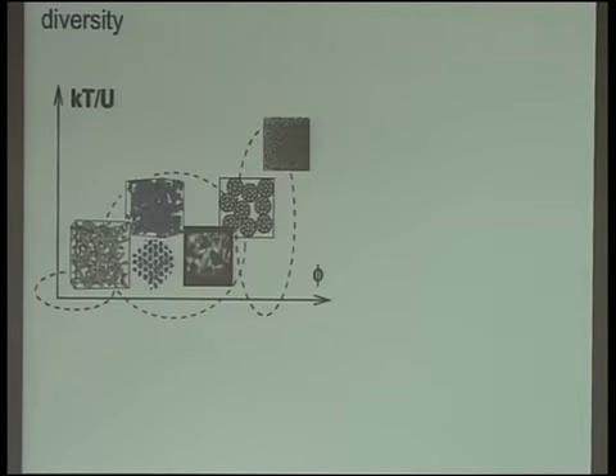Okay, so as I said, let's start from a case that is very typical of soft matter. You have a suspension of colloidal particles, and typically in experiments you can control very well the strength of the attraction between the particles, so you have particles that can stick together, and the solid volume fraction, so the amount of particles that you put in the solution. And in fact you realize that by playing with these control parameters, but also with the processing conditions, you can get a number of very different microstructures, going from very fractal thin gels up to dense porous solids and fairly homogeneous amorphous solids and glasses. And the diversity of these structures is amazing.